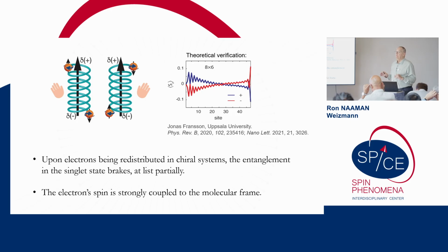Another thing that we verified with this measurement is that the spins are closely coupled to the molecular frame. In molecules, people do EPR measurements, electron paramagnetic resonance, and the EPR measurements are based on the fact that the electron is not coupled to the molecular frame. So you apply a magnetic field, the electron is now aligned according to the magnetic field, but the molecule can rotate freely. Here that's not the case.